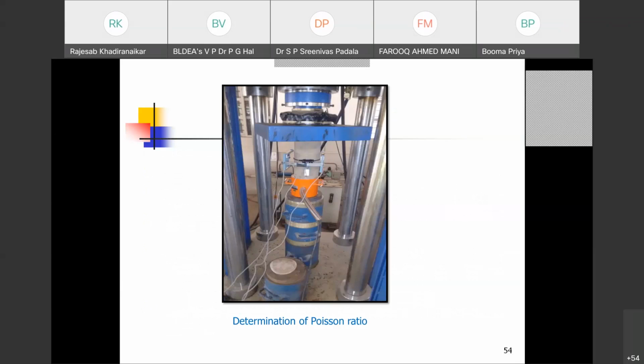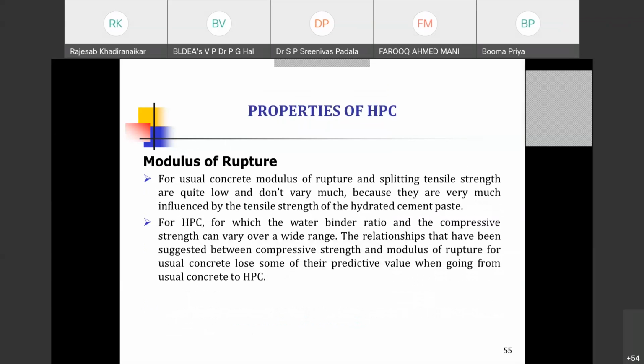This is the experiment conducted in our laboratory for high performance concrete. Then the modulus of rupture. For usual concrete, the modulus of rupture and the splitting tensile strength are quite low and do not vary much, because they are very much influenced by the tensile strength of hydrated cement paste. For high performance concrete, the water binder ratio is low and paste content is higher, and the compressive strength varies over a wide range. So the relationships that have been suggested between compressive strength and the modulus of rupture for usual concrete lose some of their predictive value when going from usual concrete to HPC, due to a change in the composition of the mix.